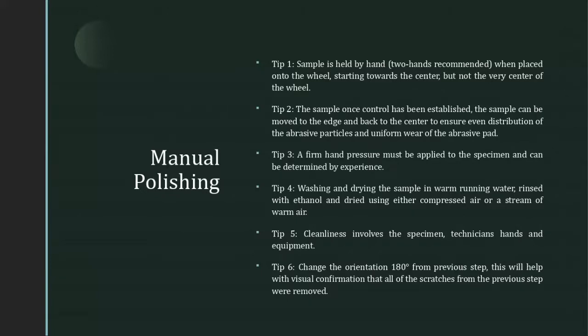And then the last one is to change the orientation. Previously I mentioned that you have to get rid of the previous damage created by the polishing or grinding steps prior, and this is one of the ways you could determine that. Other books will say 90 or 45 degree orientation changes. I do 180 degrees just because it's easier, because the disc is circular.